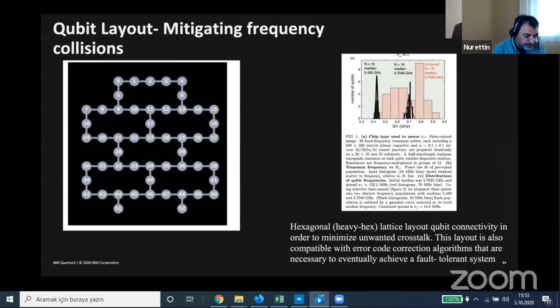What's shown in this figure here, in the pink data, is the frequency distribution. You can see here the spread is quite high, and actually most of the variation is attributed to the Josephson junction, so variations in terms of its size and so on. And what's shown in black here is a process where we introduce a laser anneal that can basically shift the frequency as we need.